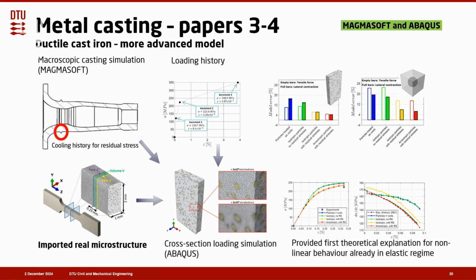Is it appearing? No, okay. But particles are treated as voids to the left. That gives a huge deviation. Then isotropic particles with no residual stresses. Then isotropic particles with residual stresses. And then finally, anisotropic particles with residual stresses. And that's what gives the best agreement.